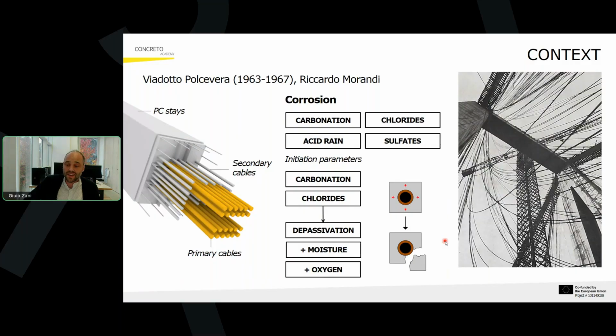And this is a picture from the construction site in which you see a phase of construction of the stays. So this is still under investigation, but also in this case, one candidate cause of the collapse of this bridge is corrosion. So we know now that corrosion is a big issue in reinforced concrete. We have several initiation parameters like carbonation, the presence of chlorides, acid rains, and sulfates, but this is not enough.